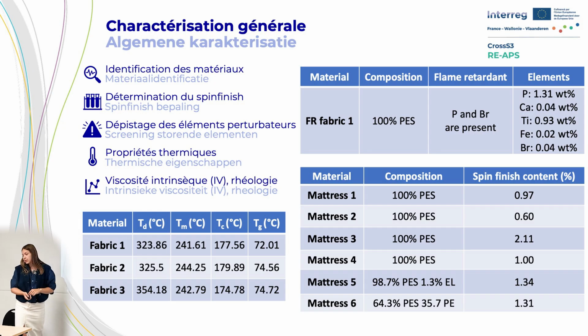So in practice, the characterization includes several analyses. For example, material identification, where we analyze the composition of the material. Also, we do a screening of elements like flame retardants and other disturbing elements. Thermal properties are also important for our thermomechanical recycling. With TGA we can analyze degradation temperature, and with DSC we can analyze the melting, crystallization and glass transition temperature.